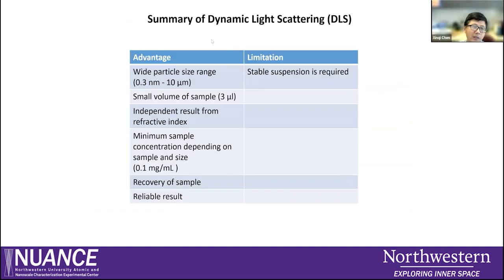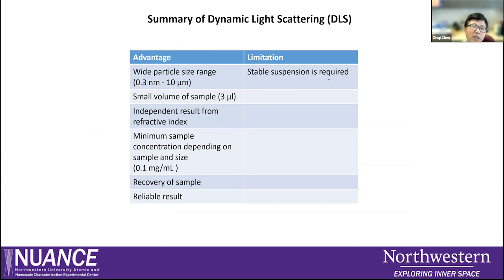In summary, the advantages of DLS are: wide size range, small sample volume, results independent of refractive index, concentration detection capability, and complete sample recovery after measurement. The key limitation is that you must prepare a very stable suspension.